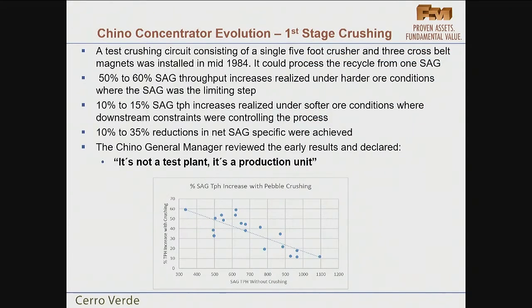So we built a test crushing circuit with a single 5-foot crusher and 3 cross belt magnets, which could process the material from one of the SAG mills. And we saw immediately 50 to 60% SAG throughput increases under the hard ore conditions, that reduced as the ore got softer as downstream constraints came into play. There were pretty significant reductions in SAG specific energy also.